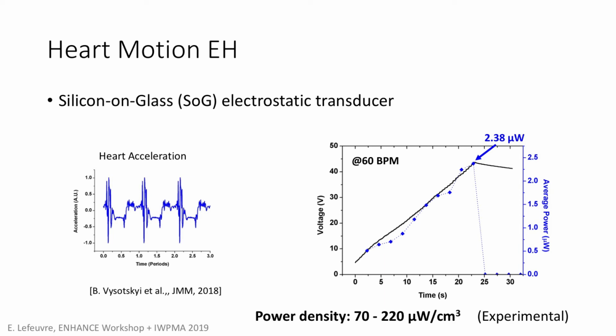So what we can understand from this slope is that we must maintain the voltage below 40 volts to get a continuous operation. And if we calculate the slope here, we have the average power that is provided, and it is in the range of 2 microwatts for this very small device. So the performance is totally acceptable. The power density, if we consider heartbeat, is about 70 microwatts per cubic centimeter. And if we apply harmonic vibration, which is not the case of the Hertz, of course, but for other applications, we can have up to 220 microwatts with the same voltage.